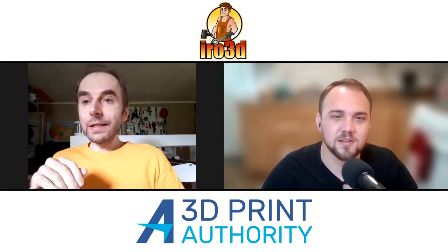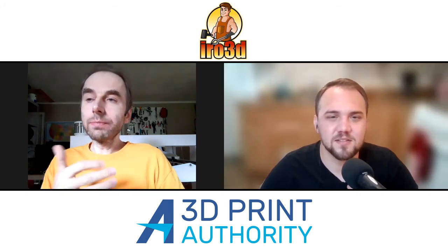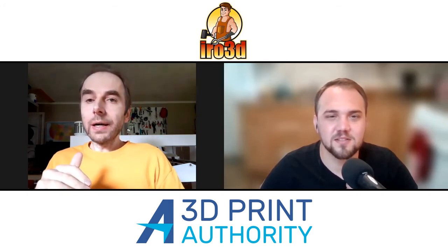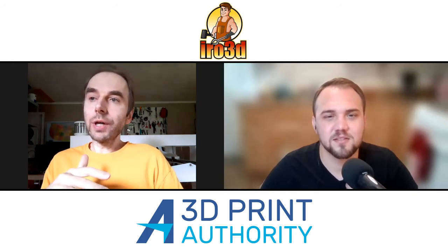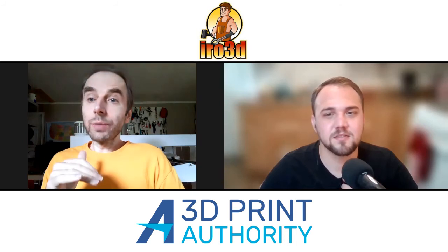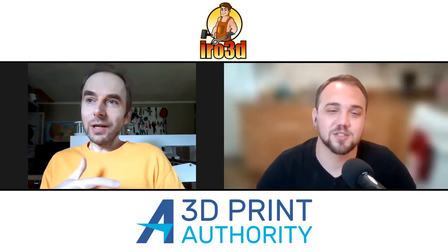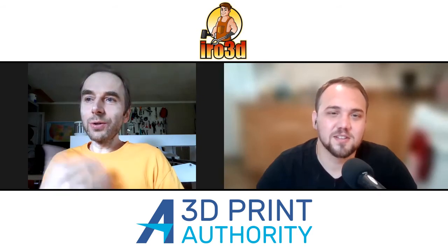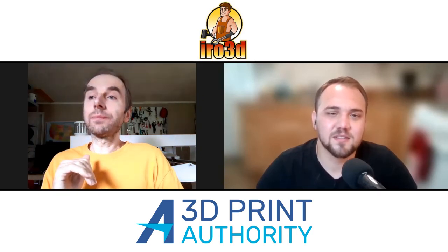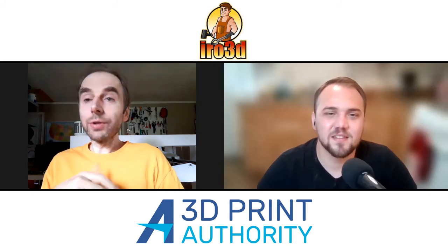If you warm it up very, very fast, then it will probably be okay. But if you take your time and do it slowly, you'll have a good amount of carbon, and your part would contain lots of carbon. And if it contains way too much carbon, it might not even infill, because graphite is not wettable by the molten metal.